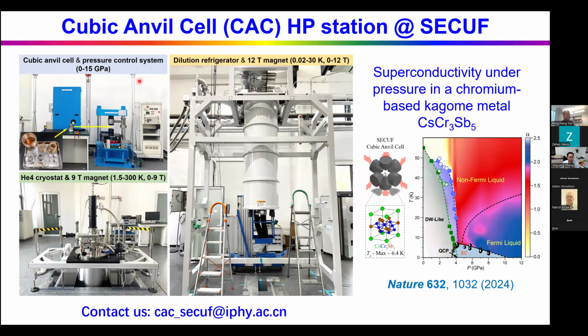This is for the high pressure. We can reach 15 GPa. Then we integrate the cubic anvil cell with the traditional helium-4 cryostat, and we also have a dilution refrigerator with a superconducting magnet, so we can reach down to 50 millikelvin and 12 Tesla under a high pressure of 15 gigapascal by using this technique.